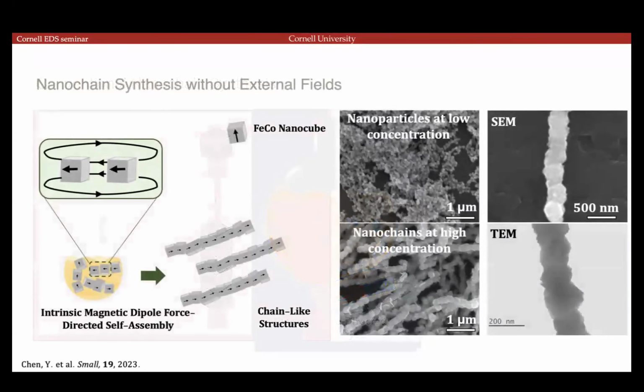In our case, though, our particles are so strongly magnetic that we don't need to apply an external field. They just self-align and self-assemble into nanochains during the synthesis process. So if you synthesize a sufficient concentration of these particles within the solution, they'll be able to find each other and spontaneously form a self-assembled nanochain that is well connected.